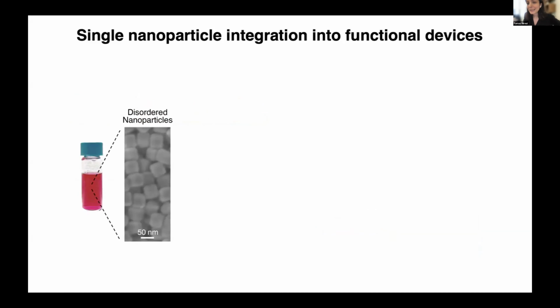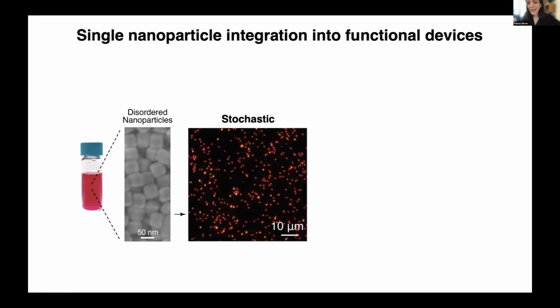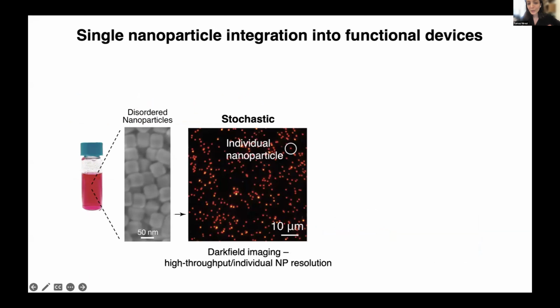Now you can imagine that is a challenging task. Nanoparticles are made in solution, so they're stochastic. Here I'm showing you as an example just a cluster of gold nanocubes that have been colloidally synthesized. So if we have them on a substrate at low density, you can see how the particles are stochastic. And what I'm showing you here is a dark field image where individual red dots correspond to an individual nanocube, emphasizing that dark field imaging actually provides us with a high resolution yet high throughput imaging approach to be able to characterize distribution of these nanoparticles.